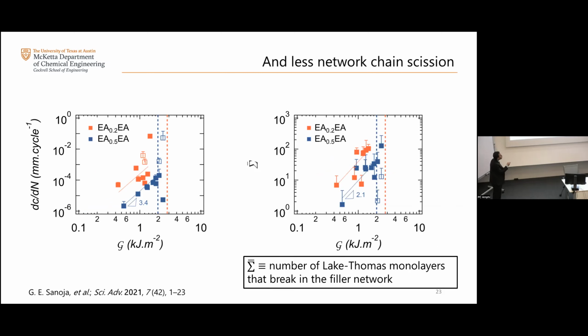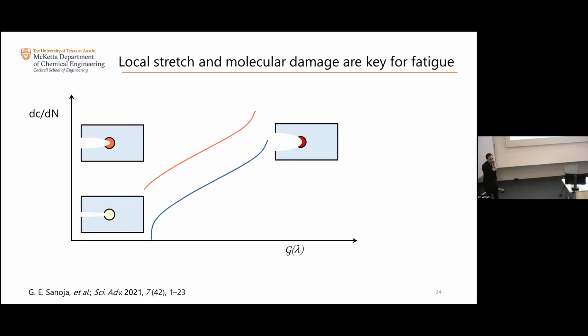Again, I'm only focusing on the average. And what you see is that on average, and the data is very, very scattered, and I acknowledge that, but basically what it seems to be happening is that the systems that are more fatigue resistant actually undergo less damage than the systems that are actually tougher. The red system seems to always have more damage ahead of the crack tip when you fracture them at the same level of G. So when the amount of energy that you apply to that crack is the same, effectively you have more damage. And the reason is summarized, or we think it's summarized, in this scheme once again.